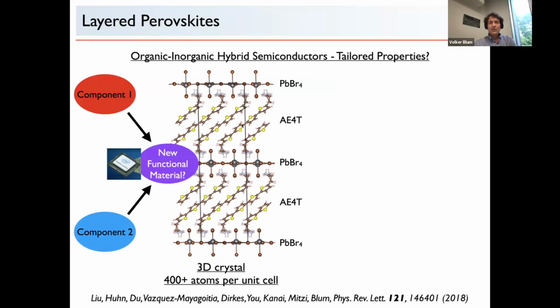perovskite is that the organic functionality is optically active and the inorganic functionality is also optically active. So then you can play tricks like having excitons transfer from one component to the other and so on. But more generally, what you have here is the full flexibility of organic chemistry. So we have one component which is organic, and you can tailor that. And then you have the flexibility of the inorganic space that you can use, because lead bromide is not the only option.